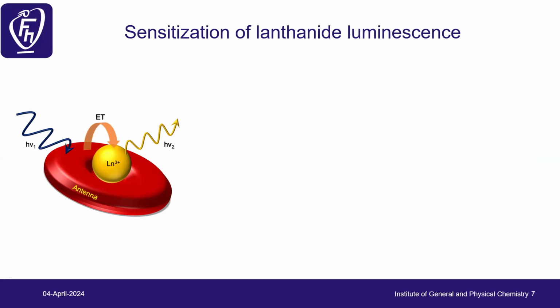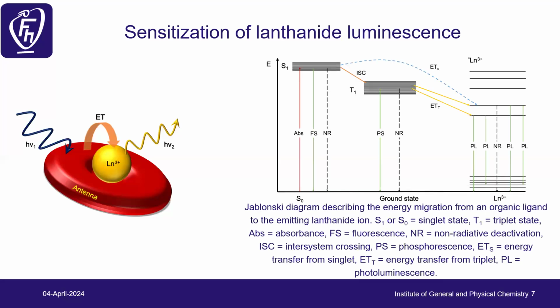Because the transitions are partially forbidden, they have low molar absorption coefficients, so you need high energy to excite the electrons. To overcome this, we can use the antenna effect. We can use an organic dye, such as a beta-diketonate, to absorb the light, and then that energy is transferred to the nearby lanthanide, which will emit its unique emission. On this Jablonski diagram we can see that we absorb from the singlet ground state to an excited state, from where there are a few ways the electron can relax.